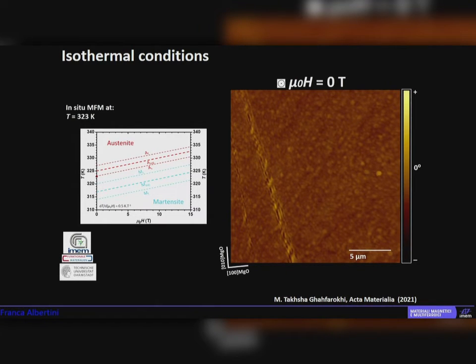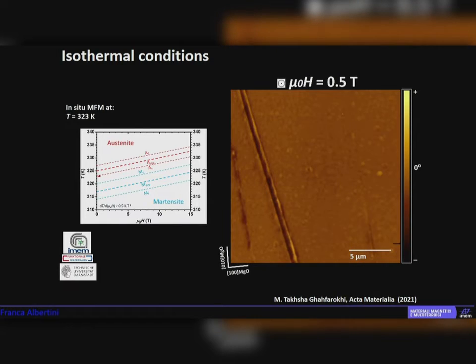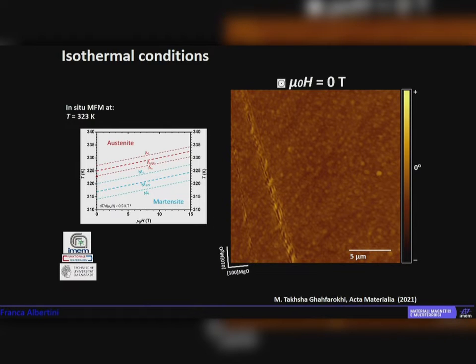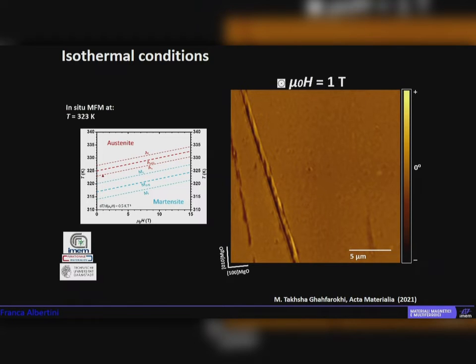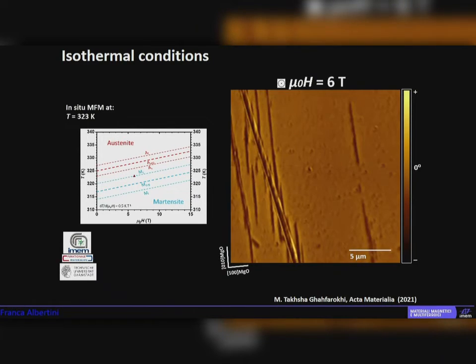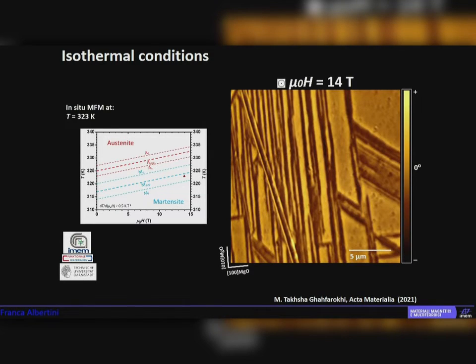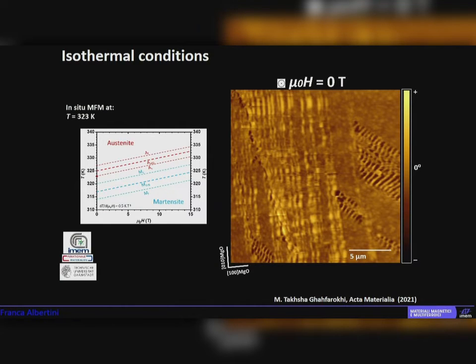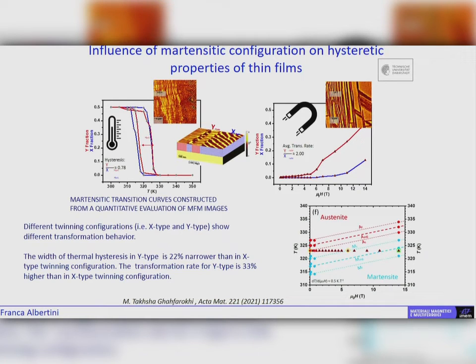Okay, this is the second experiment. In this case, we have applied a magnetic field at 323 Kelvin and in the austenitic phase, and by applying the magnetic field we cross the transformation temperature, the Martensitic start temperature, and we obtain the Martensitic structure by applying the magnetic field. And in this case we have not obtained the full transformation due to the very high field needed to obtain this full transformation, but we have been able from the different images to derive the Martensitic transformation curves for both the different microstructures.